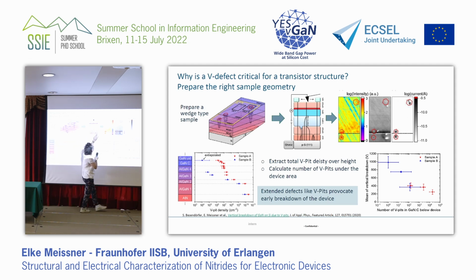You do the same experiment and you find back the leakage spots at the places that you can correlate to the V-pits. And then you make the plots. Then you calculate what you see from all your pictures, which means that you count the number of V-pits underneath the device. And then you find the number of V-pits underneath the device correlates with the good and the bad samples. And then you say, now I know that underneath these samples we have more V-pits than on the other one. The total dislocation density is the same. This is how you do it. So here you have V-pit density as it is counted, and here you correlate it to the breakdown voltage.